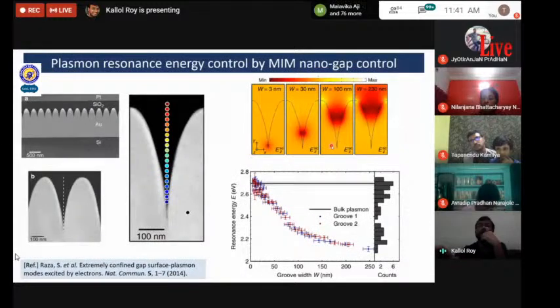So another example of such light confinement is something you can achieve in a metal interface. This graph illustrates different plasmon mode energies at different gap sizes. Again, I should mention the previous one was a metal dielectric interface, whereas this one is a metal interface, where metals are placed at a small distance. For example, this one has a 3 nanometer gap, whereas another is 30 nanometer, and so on. You can see the effective mode energy changes. As we make the gap smaller, the resonance energy is increasing.